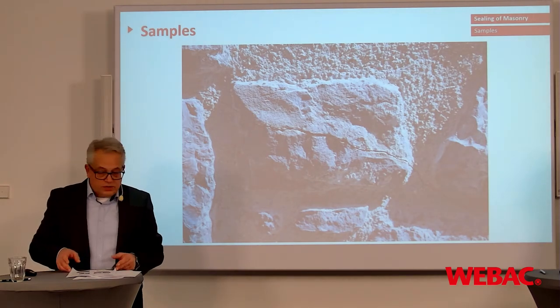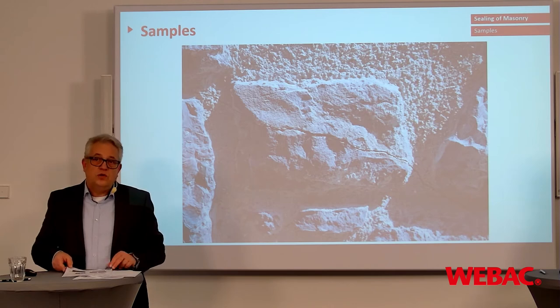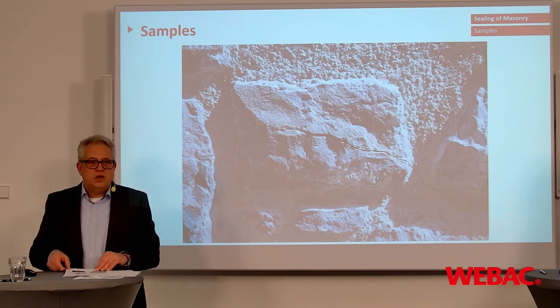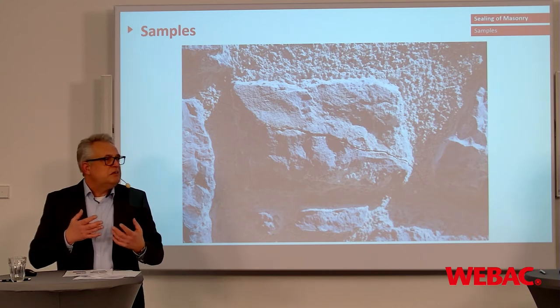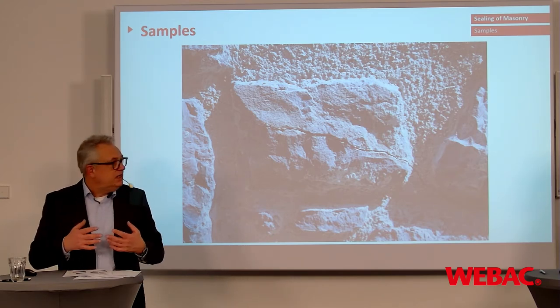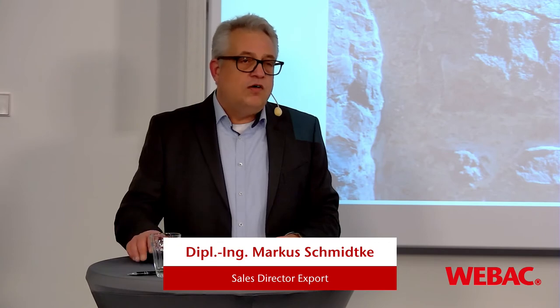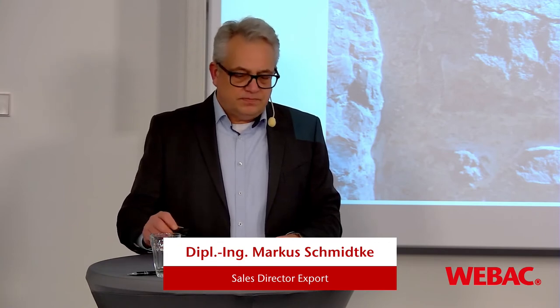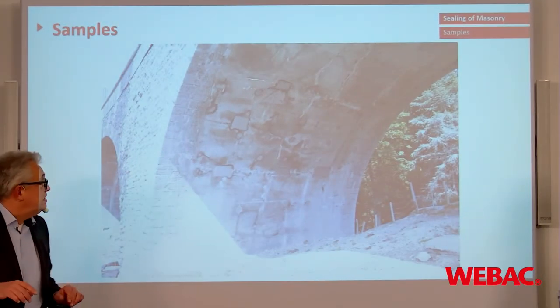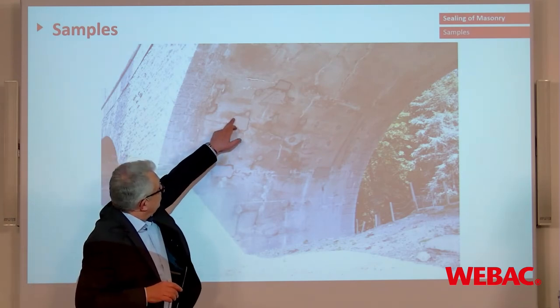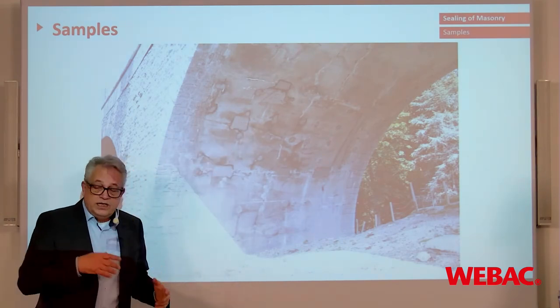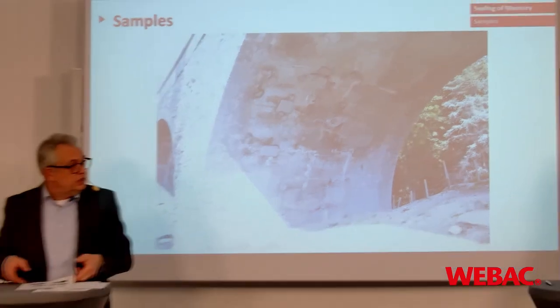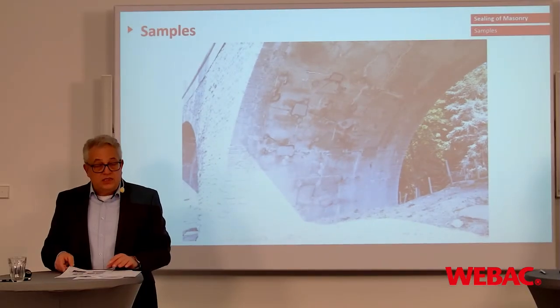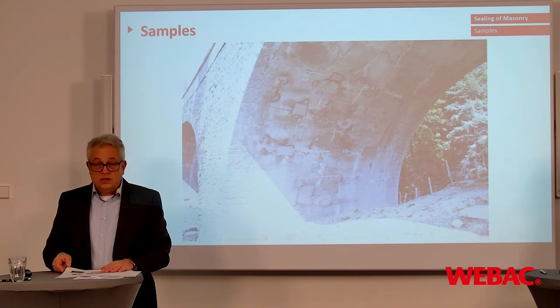So there I come back to the materials. In our days you also find polyurethanes which have the capability to, let's say, have a force transmitting behavior, and they nearly have the properties of epoxy resins. So, this was carried out, and here you see in the arc the wet spots. And especially in a mixed construction, the right choice of material was a hard polyurethane.